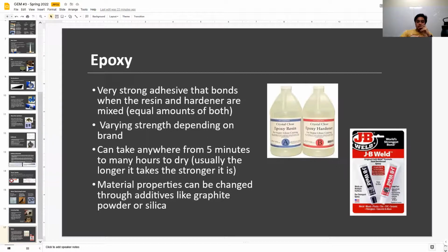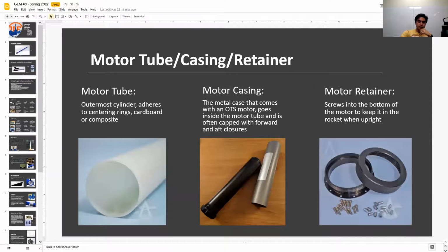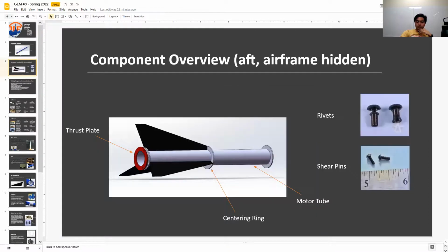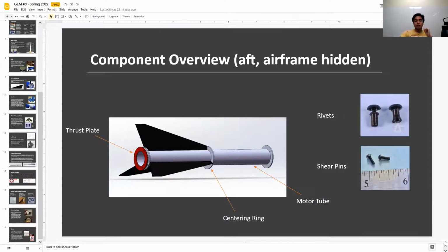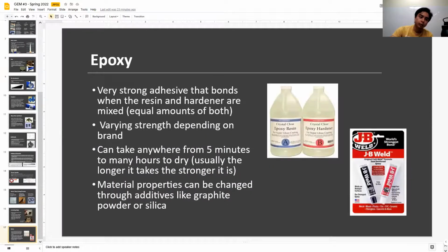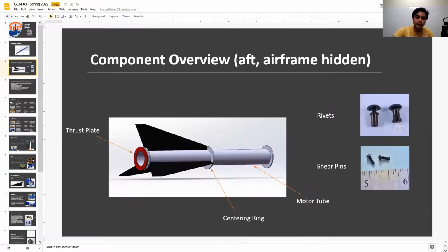So generally what we would do is when we're epoxying the centering rings and the fins, we would use Rocketpoxy on the interior of these epoxy beads because it can withstand higher temperatures before failing. JB Weld, on the other hand, while it can only withstand to, I think, around 500 degrees Fahrenheit, is significantly stronger than Rocketpoxy. So we will use JB Weld pretty much everywhere else.